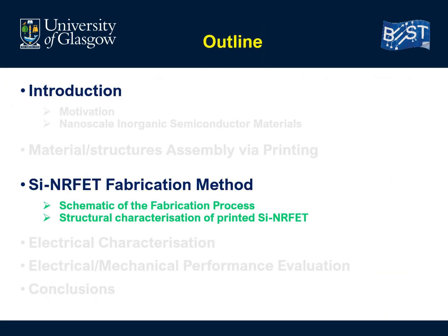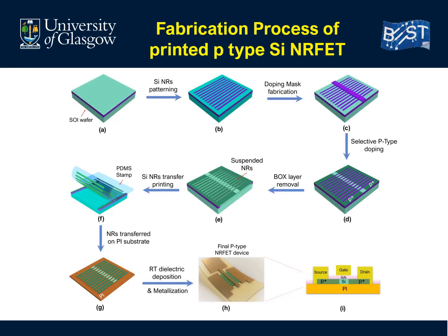In regards to the device fabrication process and the structural characterization of the printed transistors, here is the schematic of the processing steps of the P-type silicon nanoribbon field effect transistor fabricated by the transfer printing method. Since the high temperature fabrication steps such as selective doping are carried out before transfer printing, this method decouples the high temperature process steps from the low temperature steps, including the high-K room temperature silicon nitride deposited gate dielectric and metallization to deposit metal contacts for the final device.